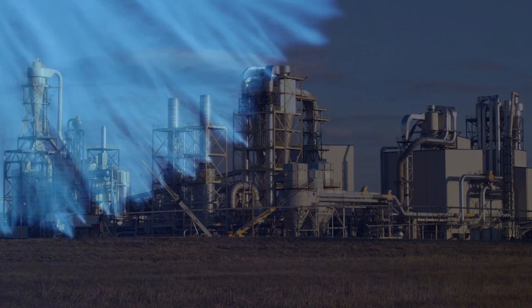So we're working at scale on making particle board by going into plants like this that basically combine wood fiber with urea formaldehyde and really nasty glue, which gives off bad emissions. And we're saying, look, we'll insert biology into the front of your plant. Instead of putting glue on your wood chips, you'll put mycelium on your wood chips, let it grow through, and you can use the same plant and equipment. These are the sorts of angles you have to take, I think, to really move the needle in terms of how we make and produce things. So our vision is mycelium in some of these old captive assets.